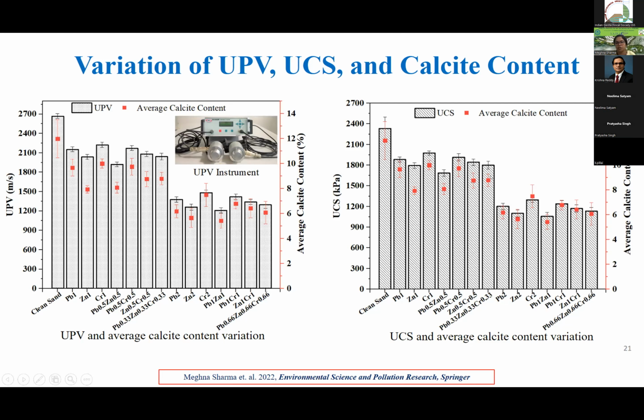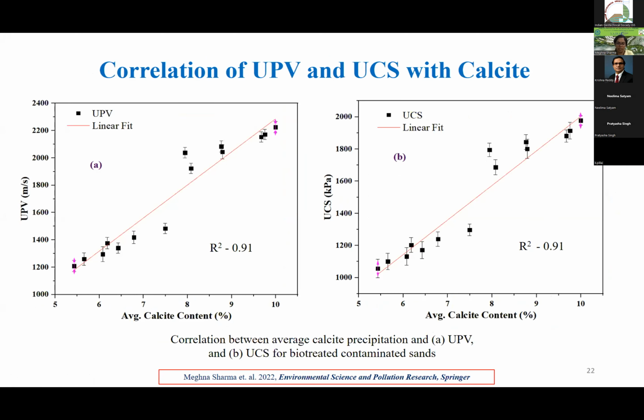And a similar relation has been seen with the UCS: clean sand has higher UCS than the contaminated one, and among the contaminated, the 1000 mg per kg sample has higher strength than the 2000 mg per kg. Okay. And the relation of ultrasonic pulse velocity and UCS with calcite content is in the journal also. This correlation was developed with contaminated soil, but with non-contaminated soil too. With the increase in calcite precipitation, the ultrasonic pulse velocity and the unconfined compressive strength increase. This means calcite precipitation is the hero of this process. If calcite precipitation is there, everything can be done, but it should be uniform whenever required, or if a thick crust layer is required, for wind erosion, then it should be there.